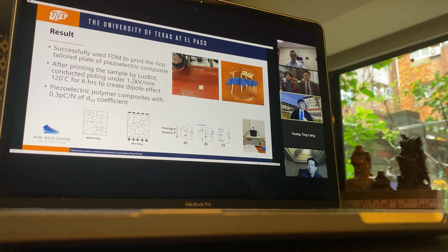Before poling, the dipoles are arranged randomly in the piezoelectric material. They will point to different angles of direction. After poling, they will align toward the same direction. As a result, the material will gain a polarization, and if there is any deformation, the current will come out from the material. So in the end, we had a good composite with 0.3 picocoulomb per Newton of the piezoelectric constant.